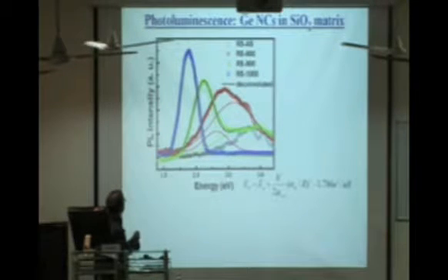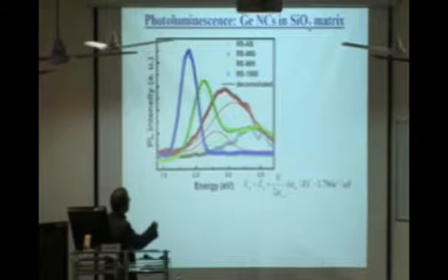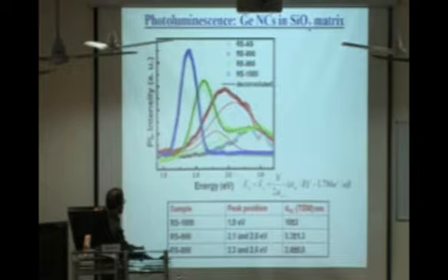These are different sample names. The sample was prepared at 1000 degrees centigrade. If samples are prepared at a lower temperature, they typically give some defects and amorphous peaks. Again, as you see, there is the same quantum size effect: if you vary the quantum dot size from 2.4 nanometer to 10 nanometer, the photoluminescence changes.